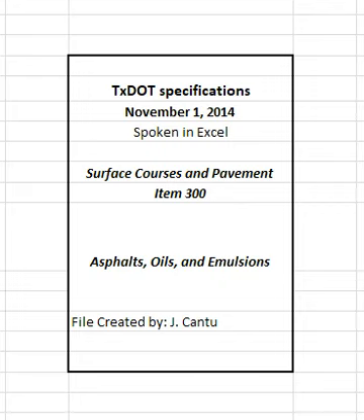Provide types I or II, containing CRM grade C, for use in hot mixed aggregate mixtures. Provide types 2 or 3, containing CRM grade B, for use in surface treatment binder. Ensure binder properties meet the requirements of Table 16. Table 16. AR binders. See table in specifications. 2.10 Performance graded binders. Provide PG binders that are smooth and homogeneous, show no separation when tested in accordance with TEX 540C, and meet the requirements of Table 17.